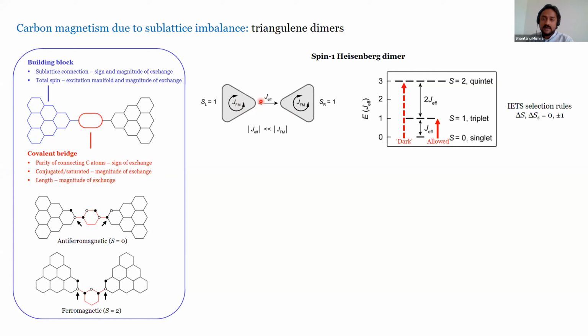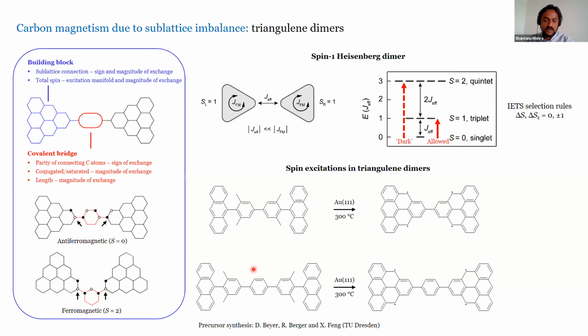So the energy spectrum should look like this. You should have a singlet ground state, a triplet first excited state, and then a quintet second excited state. So we can probably observe the singlet to triplet transition, but the singlet to quintet transition is of course forbidden by the spin selection rules that dictate that the total change in the spin quantum number should be 0 or ±1. So that's our precursor design for the two triangulene dimers.